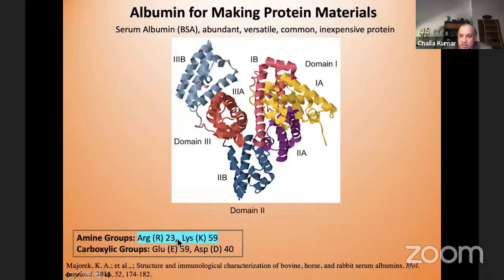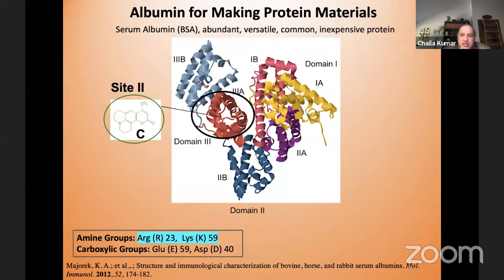And it has, very important to us, a large number of positive charge groups, arginines and lysines. And lysine has a primary amino group on it. So there are 59 of those, and most of them are on the surface, about 40 or so. So we can modify those primary amines on the surface of the molecule, because once you put it in the water, these amine groups will stick out and they're accessible for reagents. All chemistry is done in water in my lab, as I said.